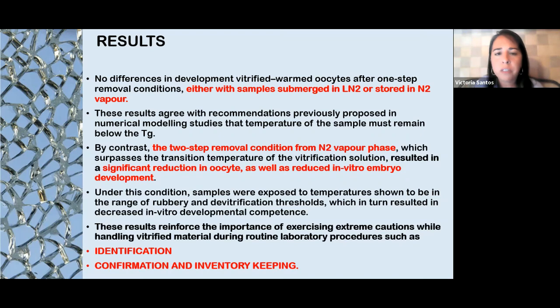Final results. There was no difference in development of vitrified warmed oocytes after one-step removal conditions, either with samples submerged or stored in nitrogen vapor. These results agreed with the recommendations previously proposed with the numerical models that the samples should remain below TG. In contrast, with the 2-step removal condition from the nitrogen vapor phase, the temperature of the sample surpassed the TG and the survival was reduced. Under these conditions, the samples were exposed to temperatures shown to be in the range of the rubbery and devitrification thresholds. These results, therefore, reinforce the importance of exercising extreme caution while handling vitrified material during routine laboratory procedures, such as identification and confirmation and inventory keeping.